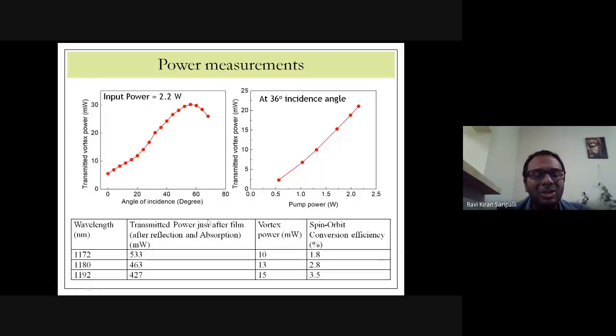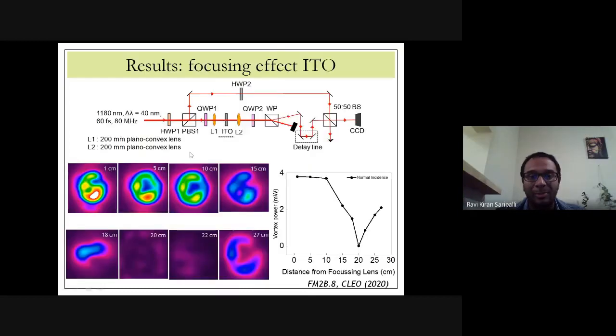Then we did some power measurements. With the angle of incidence, you see that the vortex generation is increasing, and it's a maximum at about 57 degrees. And this is consistent with other ENZ phenomena that people have observed, like the high Kerr nonlinearity or the super tunneling. Why this happens is because the dielectric displacement is continuous across the surface or the interface. And so you want to be able to maximize your transverse magnetic component of the polarization, and that happens at about this wavelength. And so that is what is happening here.